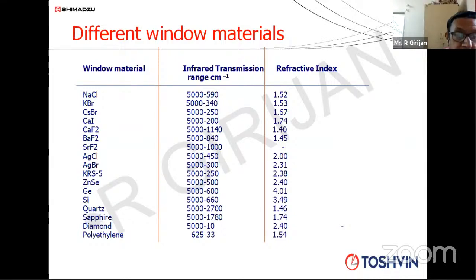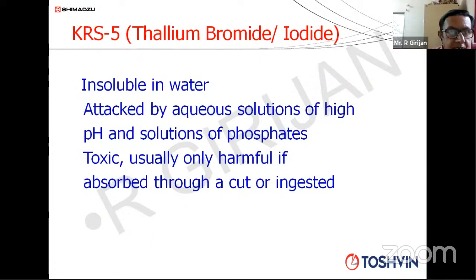Okay. But please remember, you cannot use crystals like sodium chloride or potassium bromide or cesium iodide for samples containing large amounts of water, or aqueous samples, because all these materials are highly water soluble. They can be used for non-aqueous samples. But for aqueous samples, don't use crystals like sodium chloride, potassium bromide and all, because that will spoil the crystal. For that, you have to use materials which are totally insoluble in water. Calcium fluoride, silver chloride, KRS5, zinc selenide, these are all totally insoluble in water, and they can be used for aqueous samples.